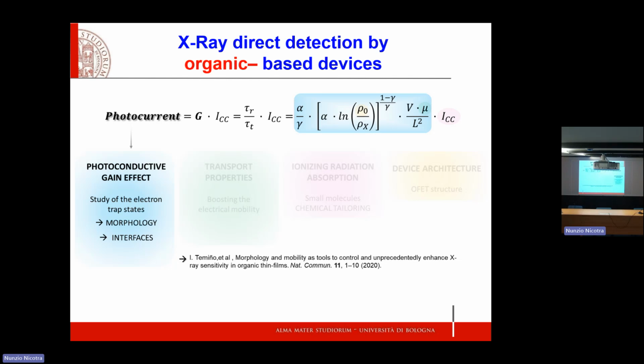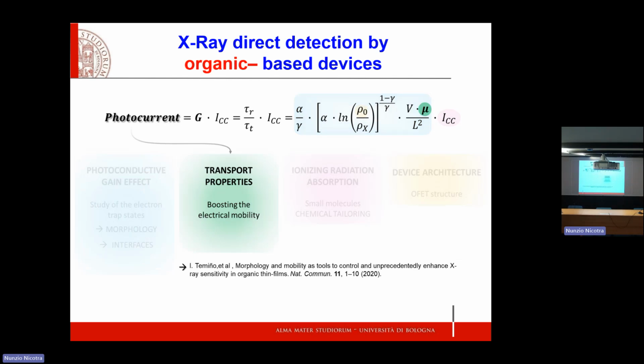The first thing we can work on is the morphology and the interface, the morphology of this polycrystalline film and the interfaces, because that's where the defects, the electron traps are located. Then we can play with the mobility, you see, direct proportionality. The higher the mobility, the better the gain.